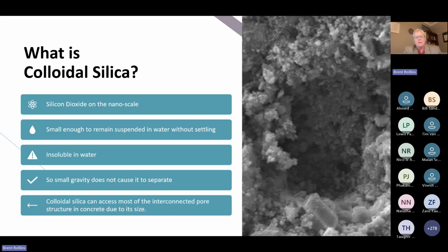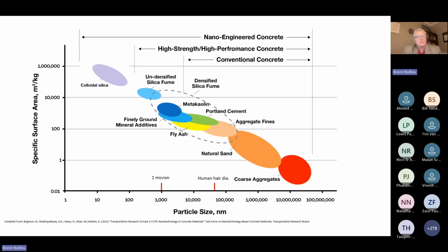To put that into further perspective, I know you like rugby there. If you imagine that the average colloidal silica particle is about the size of a rugby ball, then the average pore structure in concrete would be about 3 kilometers wide. So that's how tiny we're talking. We're talking about a very, very small material, and that size is the key to its effectiveness because it gets in deep, really, really deep, and it also is able to have very high reactivity because of that small size.